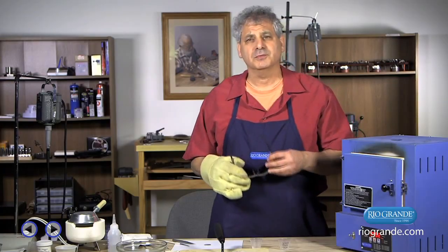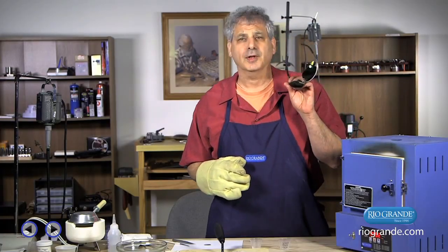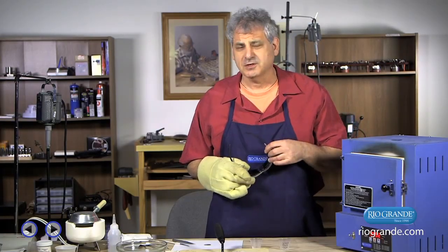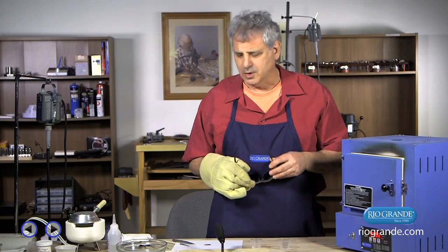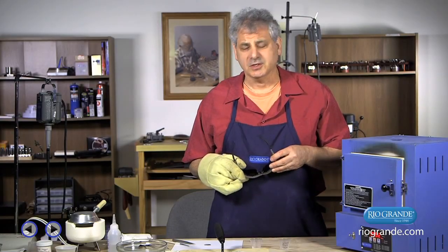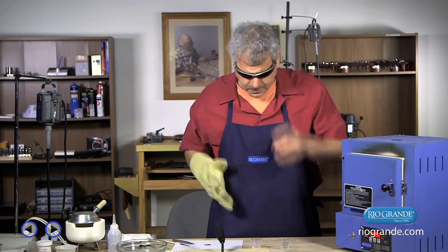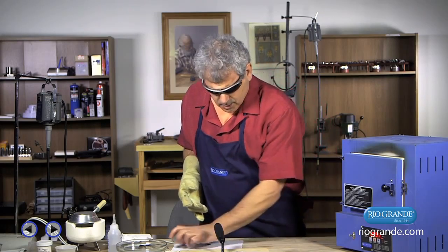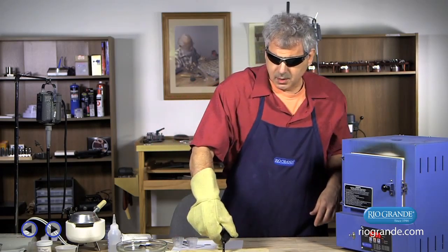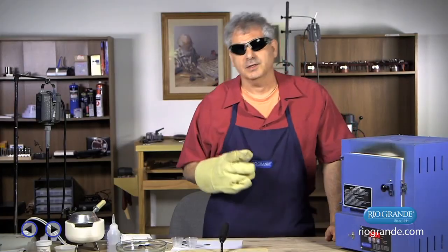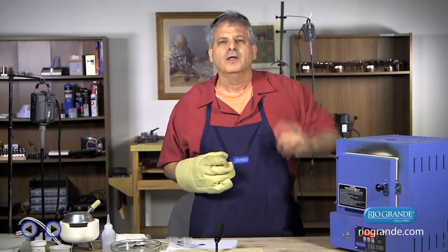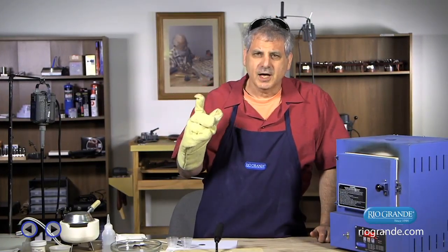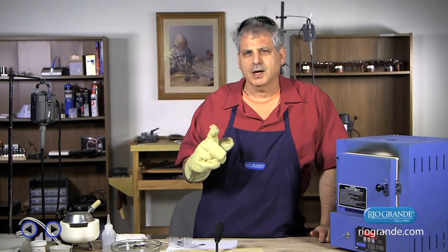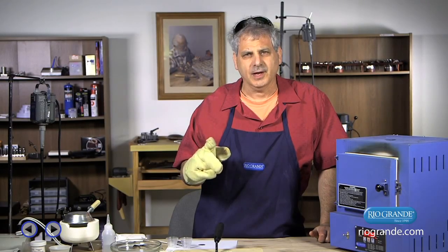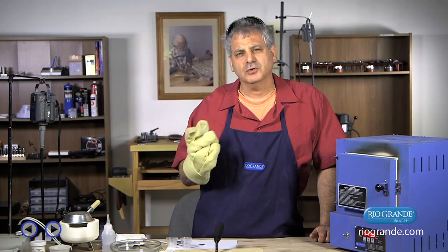This is so that I can put a hot screen and not ruin my table. I'm going to also wear some glasses that are treated to keep infrared light from giving me cataracts. If you just do a little bit of enameling, it's not going to hurt you. But I do a lot of enameling, so I wear these when I fire. And the important thing about firing is to understand that there's not a right amount of time or a right temperature to fire at. It's an internal temperature.